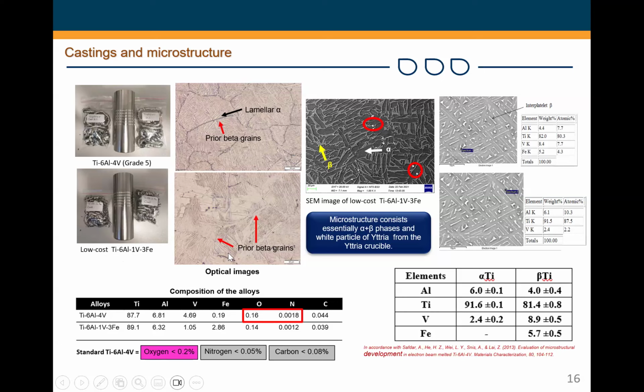And you can see that the microstructures are similar because they both have lamellar morphology, basically. So it's a fully lamellar structure, comparing the as-cast Ti64 with that of the experimental titanium alloys. And if you go to the SEM, you have higher resolution and you can see more, and you can see two distinct phases, which is the alpha phase and the beta phase. Although the result is not shown here, we did XRD analysis and we didn't find any TiFe phase in our alloy.